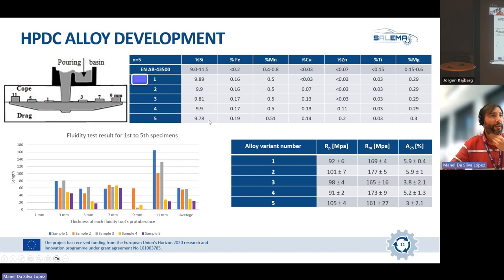One important development we have done in the project is to measure the alloy flowability. We have developed our own test that is currently under standardization. We are currently publishing a CWA from this test, and that has allowed us to predict, for instance, the loss of flowability caused by some minor additions. Here we can see that small additions of zinc greatly reduce the flowability of the alloy, by half. So it's a very important issue, not just the effect that the increase in impurities will have on the mechanical properties of the alloy, which remain more or less constant, as we have also checked, but also the castability or processability of these alloys.